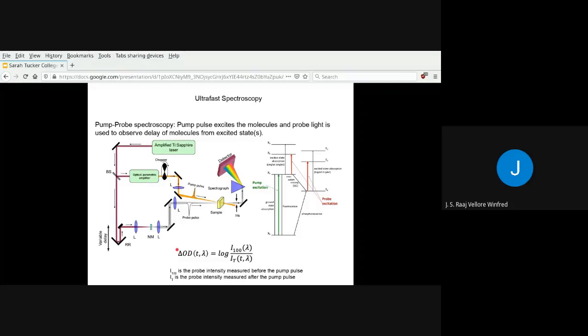The decay of these excited states is measured by the change in the optical density. The optical density is calculated by this expression that you see over here, where the numerator is the probe intensity measured before the pump pulse, and the denominator is the probe intensity measured after the pump pulse.